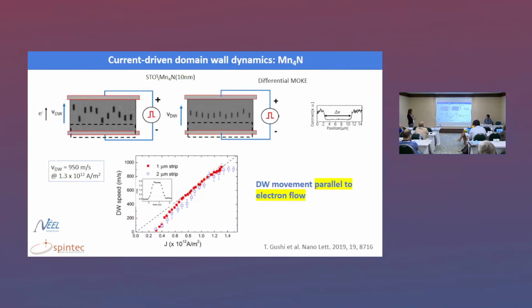The main talk is about current-driven domain wall dynamics. For this, our samples were patterned into strips, 2 micron and 1 micron strips. These are differential Kerr images. The contrast that you see corresponds to the displacement of the domain wall driven by a current pulse, and this length stays the same. So there is very small dispersion of the displacement of domain walls with the current, also related to the fact that we have a crystalline system in which we have very small pinning of domain walls.